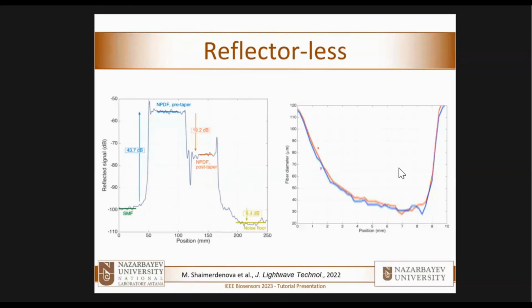So I'm not lying when I say that if you don't have a fiber with high scattering, you can't do this. In this case, the scattering is about 43 dB away, but some of the fibers that we have have about 50 dB more scattering, a fiber engineered to scatter 10,000 times more than standard fiber. Obviously, that's quite an engineering process. Here we made a taper with a diameter of 30 microns. This is not a fiber with 1 micron diameter, as you find in some works that try to get the diameter down but don't have very high reliability. These tapers survive when you make a biological measurement.